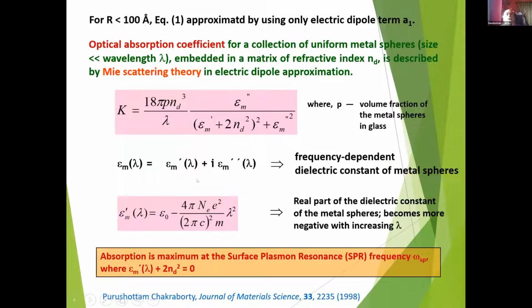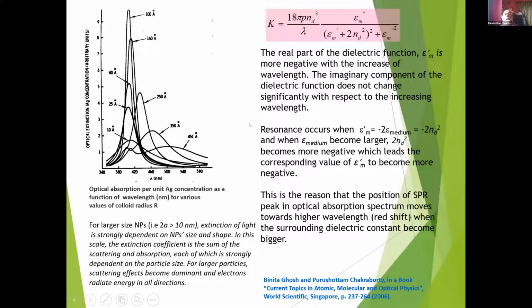Therefore you can see that k can be maximized by minimizing the denominator. So this has to be 0. That means epsilon m single prime equals minus 2 nd square, isn't it? So you can have an optical resonance.